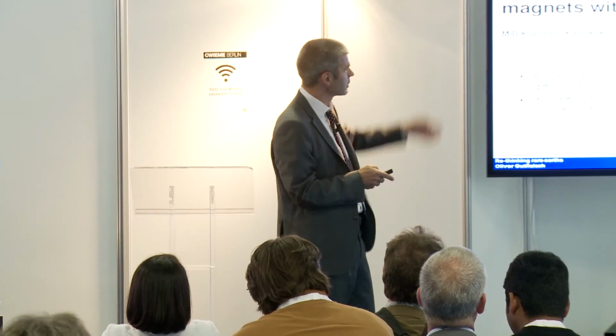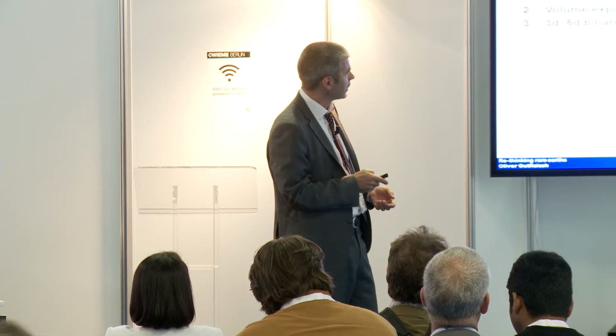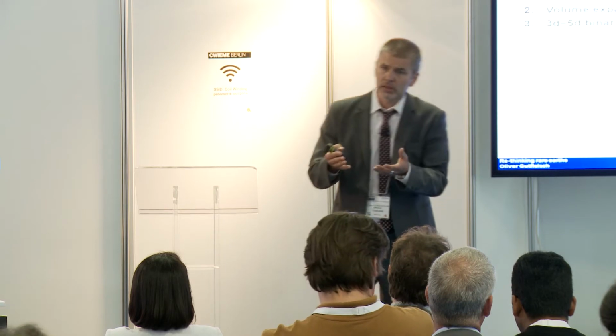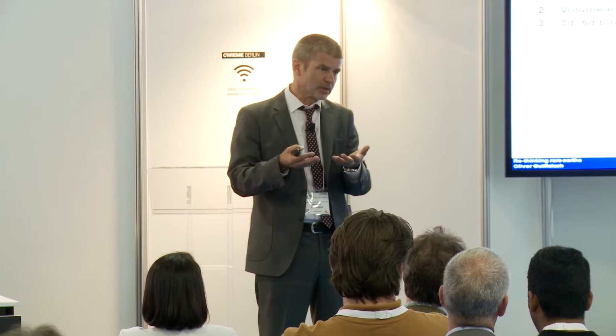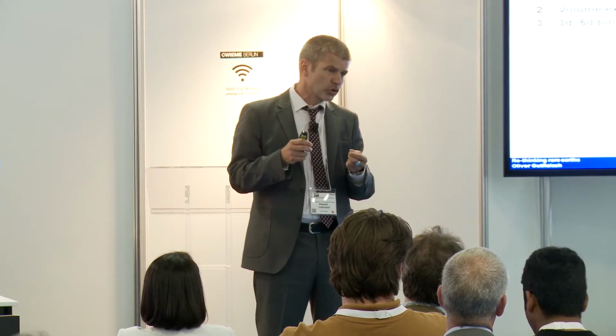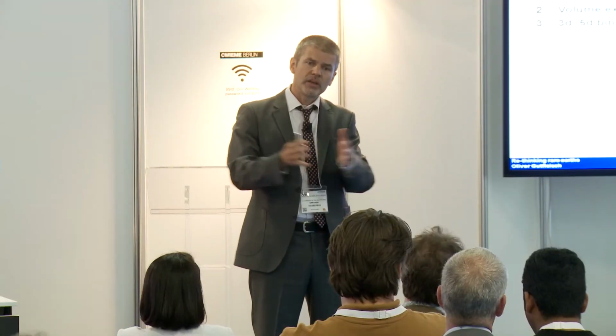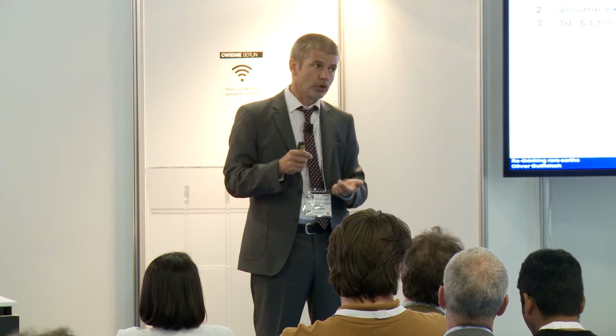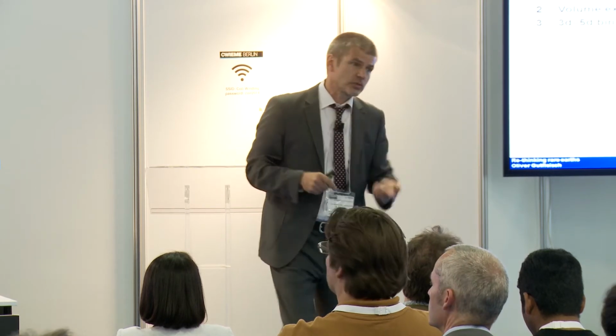Yeah, and we drew up some lines for how we can get towards high-performance magnets in the recent publication here. And the idea, just to give you one or two examples: iron cobalt has the highest magnetization, 2.35 Tesla, but it's cubic. It has no anisotropy. If we find elements we could add to this material to make it tetragonally distorted, to have some anisotropy, then we would have an interesting material for a permanent magnet. So that would be one strategy, what I mean with non-cubicity.